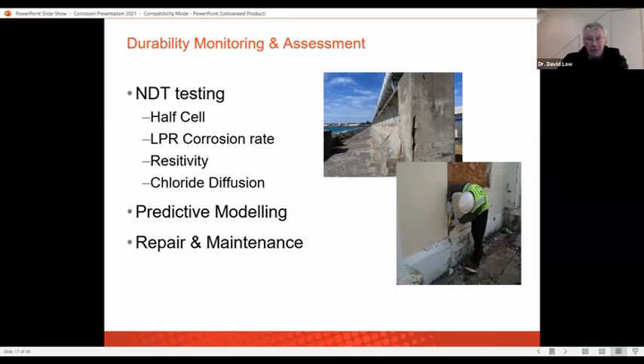We can also look at resistivity. What's the resistivity of our concrete? If we've got a lot of chloride ions in there, the resistivity will drop. If it's very damp, if it's moist, the resistivity will drop. And we can also look at what's happening. What is the chloride diffusion coefficient? What's the rate that our chlorides are coming in through our concrete?